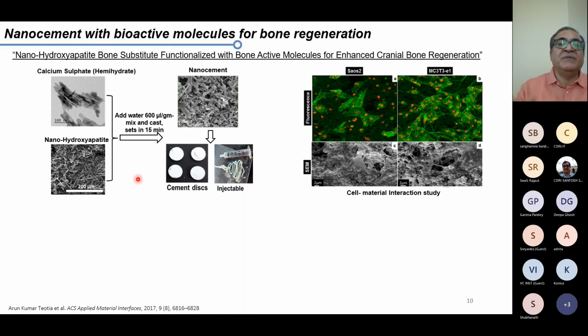That is why I am using the word bone cement. It becomes a cement, but it is actually calcium sulfate and nanohydroxyapatite. Previously calcium phosphate was used, and with calcium phosphate and hydroxyapatite you can again get the same type of cement material, but calcium phosphate is not water soluble, so bone growth was difficult in these types of materials. But lately, people working in this area have designed this material as calcium sulfate, which is water soluble.